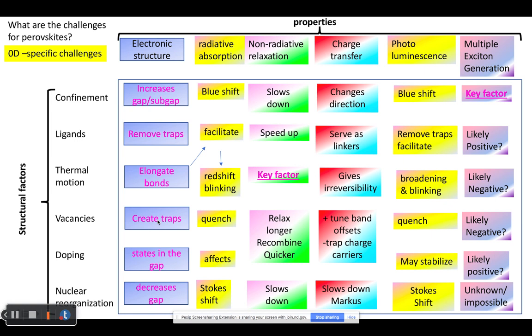Vacancies, when they happen, create traps, and they are typically unfavorable for conductivity and for absorption of light. For non-radiative relaxation, they create traps, and relaxation is typically slowed down, but recombination sometimes goes quicker on trapped sites. And the same is correct for doping. For charge transfer, the traps and doping may tune alignment of bands, which is a good plus, but they may trap charge and prevent it from being transferred, which is negative. And for photoluminescence, vacancies typically quench it, forbid it, but intelligently chosen doping may stabilize and help luminescence.